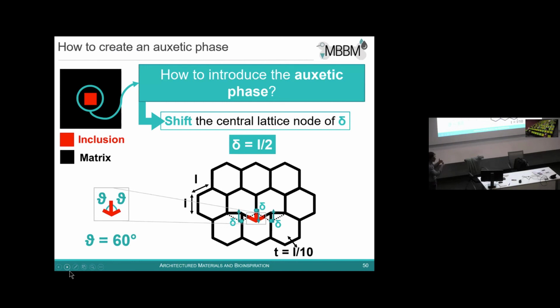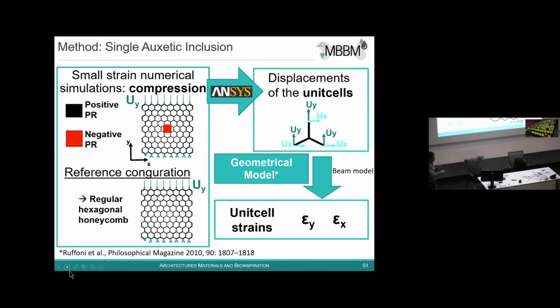joint. When the connection between three beams is one joint, we shift it down, and then we have an auxetic inclusion. The lattice is otherwise very big, and we then simulated, when we compress this, what is happening at the level of this inclusion. This was the research question. So we apply a uniform compression, and we compare the behavior with respect to a regular lattice.